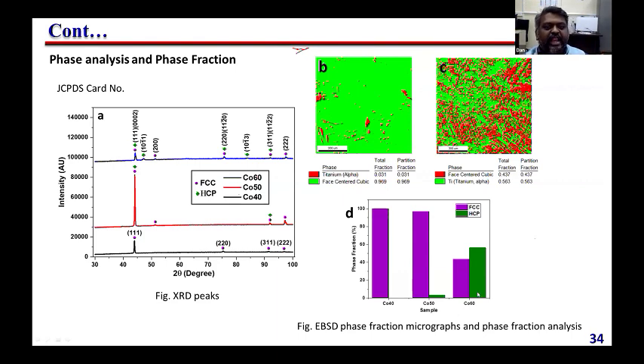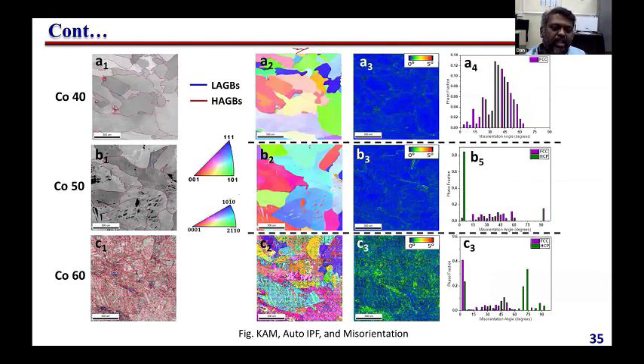Okay, so this will also enhance the strength in the mechanical properties, or if you are going for fatigue properties, some optimized dual phase structure will give better properties. So that's why we try to see this composition variation. In the case of 50%, the martensitic transformation is below 5%, but in the case of 60%, almost 50 to 55% martensitic transformation has already happened. So here you can see a large amount of high angle grain boundaries because of this transformation, because all of it nucleated at the grain boundaries. But in the first case there is no nucleation of martensitic transformation at the boundary, while in the second case, 50%, you can see certain areas having martensitic transformation, with these different colors.